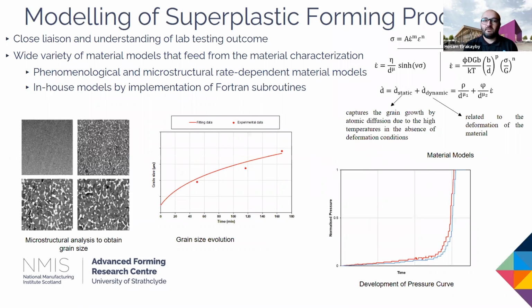As you see in the top right of the slides, there are phenomenological and microstructure rate-dependent material models that are well known and available in the public domain that we use beside other models to represent the material behavior. For example, the last constitutive equation captures the grain growth or the grain size evolution during the SPF process. This equation captures both the static grain growth by atomic diffusion due to the high temperature in the absence of deformation condition, and the other part of the equation captures dynamic grain growth, which is related to the material deformation. While the mechanical behavior itself is modeled by the viscoplastic response of the material, which is expressed by a power law-based model, for example, as in the first equation.